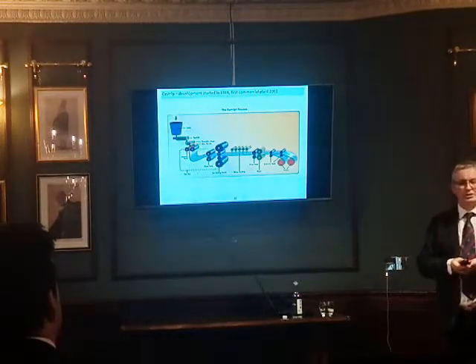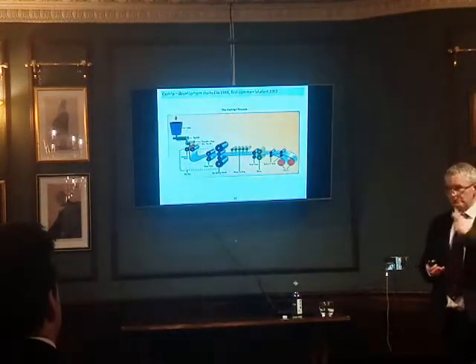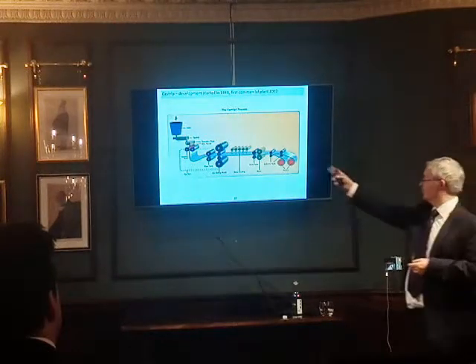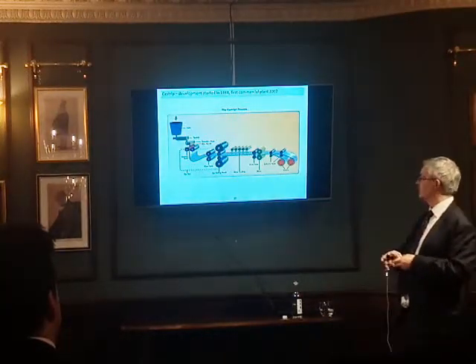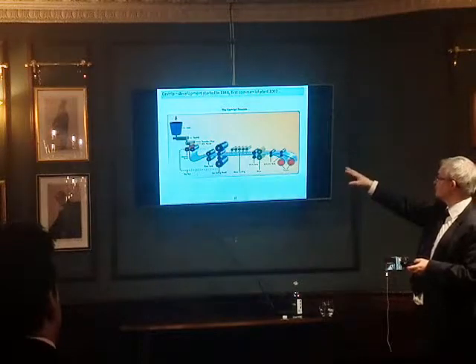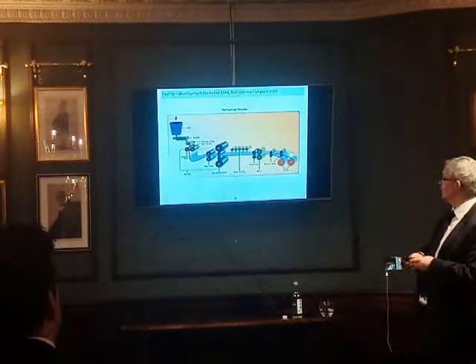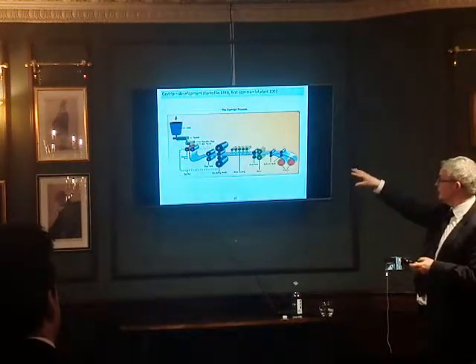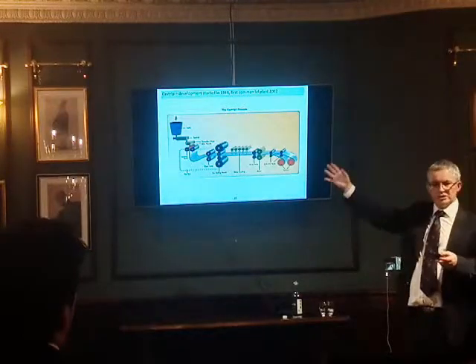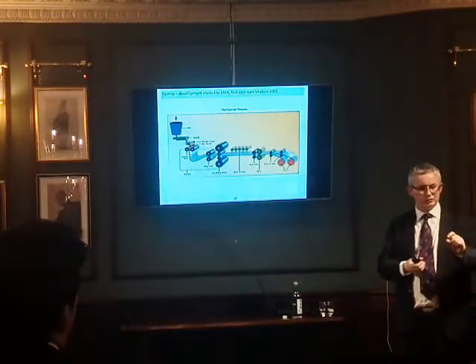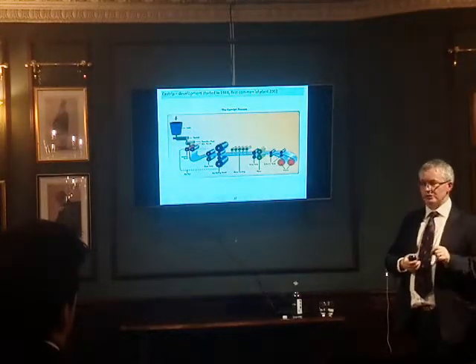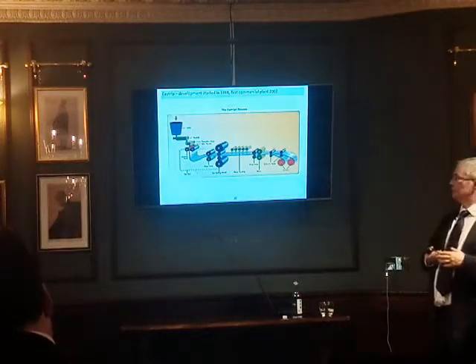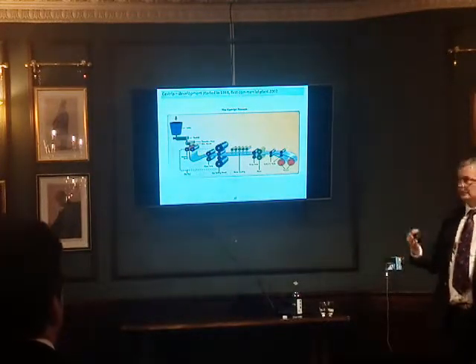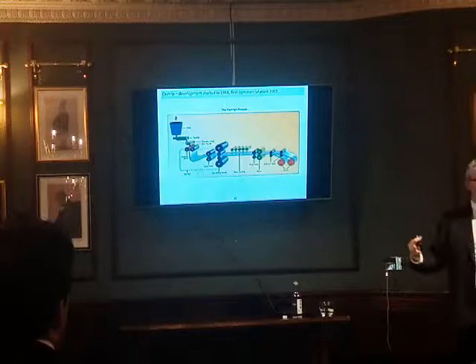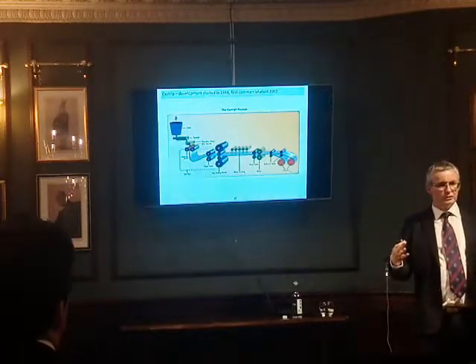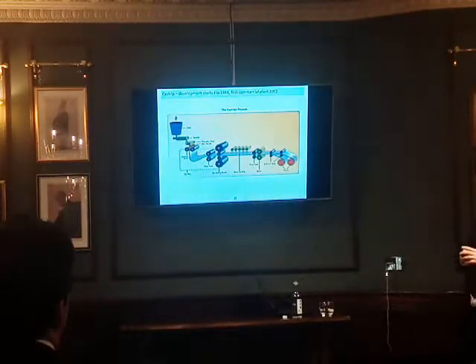Steel was being cast in a relatively large pilot plant through water-cooled copper rollers on the left-hand side, then going through various other relatively simple rollers, and minimising the rolling operation. The steel is essentially cast into the finished form as rapidly as possible, and then coiled. So very compact. This whole thing is certainly less than the 260 metres of the thin slab plant.